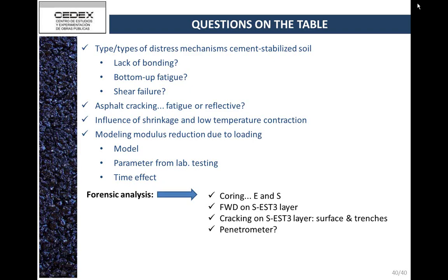I think that's consistent with some of the things that we're seeing. The slip condition or the bond condition between layers is a function of quality of the tack and also the material that's used in the tack more than maybe we realized it was.